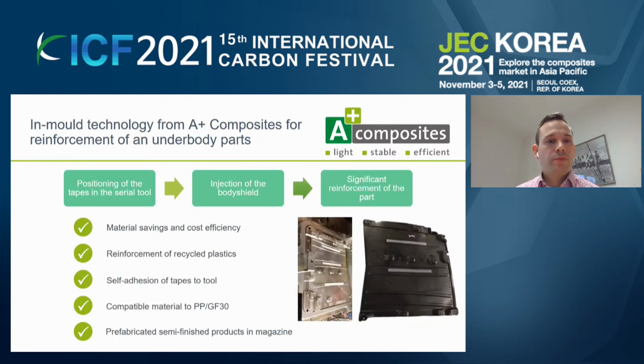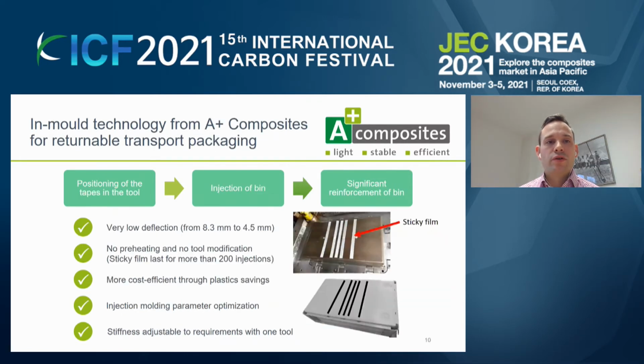We have two different examples. This is one which we developed together with Röchling. It's the underbody part, which we have reinforced with glass fiber polypropylene material, specially designed to increase the stiffness on the outside of the underbody part. And there we have used a special self-adhesion tape, so there was no need for tool changes. Another short example is returnable transport packaging. It's a bin, and here we use the carbon fiber reinforced material, which I have shown you earlier from the Soltec fibers, and there we can decrease the deflection of the bottom part by half.